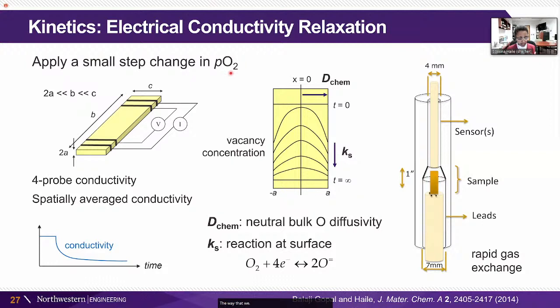The way that we do this measurement is to do a straightforward, let's call it a 4-probe conductivity measurement. And the overall idea is that if we can change the oxygen concentration in the gas phase in a very sharp and brief way, that we will see a change in conductivity that reflects that change in gas phase oxygen concentration. And the conductivity will relax to a new value. And if we track this relaxation rate, then we are able to extract out kinetic information about our material. So I like to say that, we have a very relaxed lab. We do a lot of relaxation experiments.